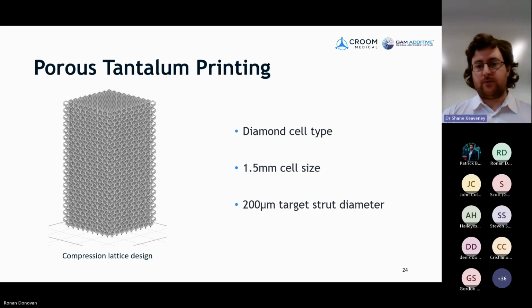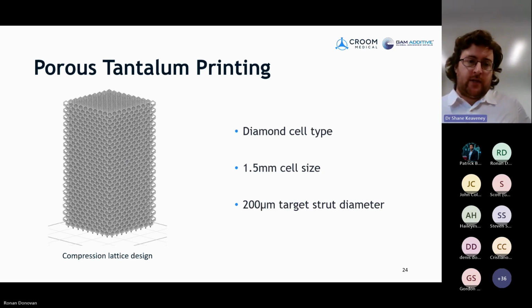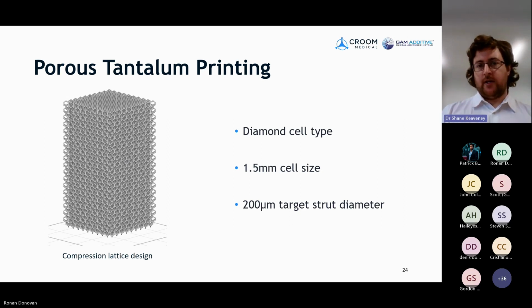Now, in terms of the porous, which is the other side of what we're looking at in an implant, we've done some work here in terms of, again, a number of DOEs to understand the process, the behavior of the printing, and the behavior of the printed structures as well. So as we've seen in a lot of the literature, we've just used a typical diamond cell here to get some nice results, 1.5 mm cell size, and we targeted a 200 micron strut diameter. And with this, I've gone for a regular lattice as opposed to stochastic just for this type of compression testing, as more consistent results give us better information here.